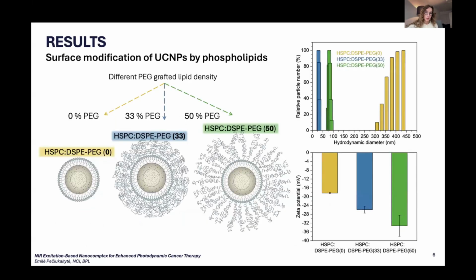So now moving on to results. In the study, we investigated 3 phospholipid coatings with different PEG-grafted lipid densities. According to theory and literature, high polyethylene glycol content should yield larger hydrodynamic sizes. However, after surface modification, the opposite trend was observed. Coatings with polyethylene glycol produced smaller hydrodynamic diameters and more negative zeta potentials, indicating good colloidal stability, while coatings without PEG resulted in particles approximately 4 times larger, with less negative zeta potential, and clear signs of agglomeration and sedimentation. For this reason, only PEG-containing coatings were selected for further experiments.